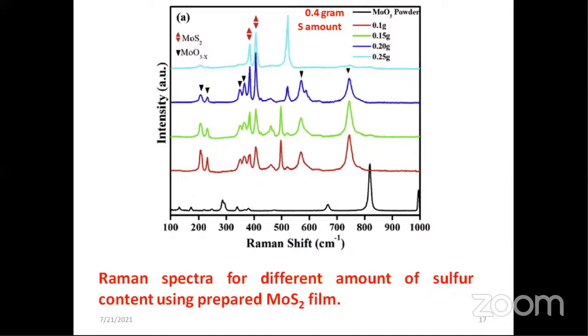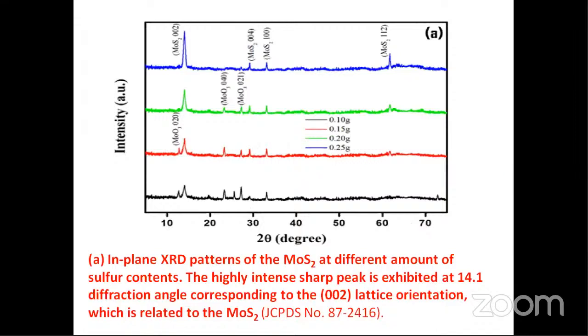This is our Raman spectra of the samples. Basically, here we are showing that the amount of sulfur is very important in this whole work. When we take a very small amount of sulfur, 0.1 gram, at 600 degrees centigrade, we found several other peaks in our Raman spectra. When we increase the amount of sulfur, we finally found very good quality MoS2, and this MoS2 film is like the standard as reported, for monolayers as well. So the sulfur precursor amount is very important in our case. And this is the XRD spectra of the MoS2 with different amounts of sulfur content.